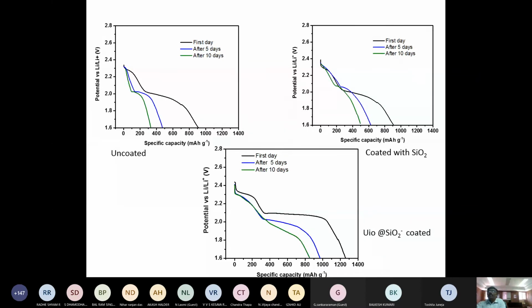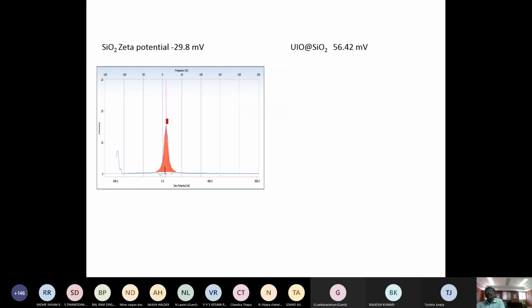Whereas in the C, the last one, on the first day it was capable of delivering 1300, and after 5 days it was able to deliver 1000 milliampere hour per gram, and after 10 days we got nearly 900 milliampere hour per gram. So this is the major advantage of coating the membrane for lithium sulfur batteries, which not only prevents the shuttling of the polysulfides, at the same time it prevents the self-discharge.